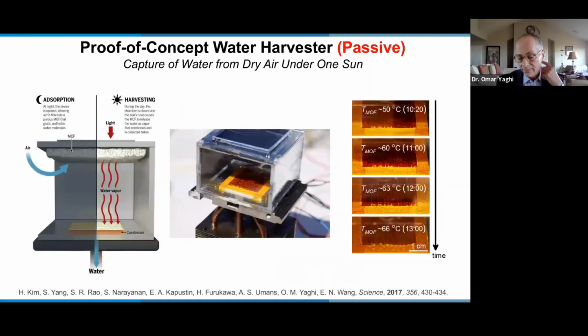So we wanted to show that in fact this works outside the laboratory. And so we have put together, in collaboration with Evelyn Wang, a device that is almost the size of a hand. And this device employed 2 grams of MOF, just 2 grams, just to demonstrate that it can work outside at a relative humidity of around 25%.